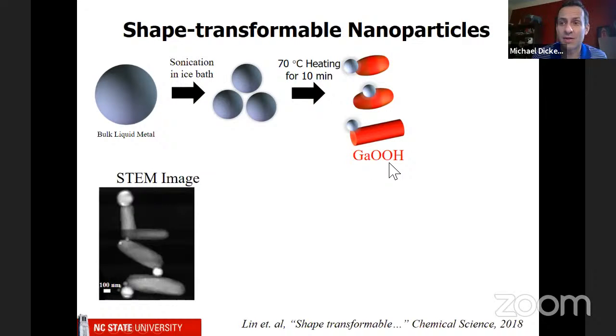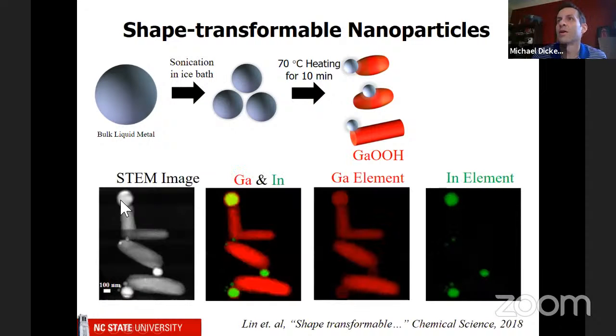And that is a solid, and it's a crystal. And this is what it looks like. It's a rod. But because these particles have gallium and indium, we also see some indium particles left behind. So if you do an analysis of this, you'll see that the rods are gallium or gallium oxyhydroxide, and the particles are indium. And so we're actually able to separate the gallium from the indium by simply reacting the gallium